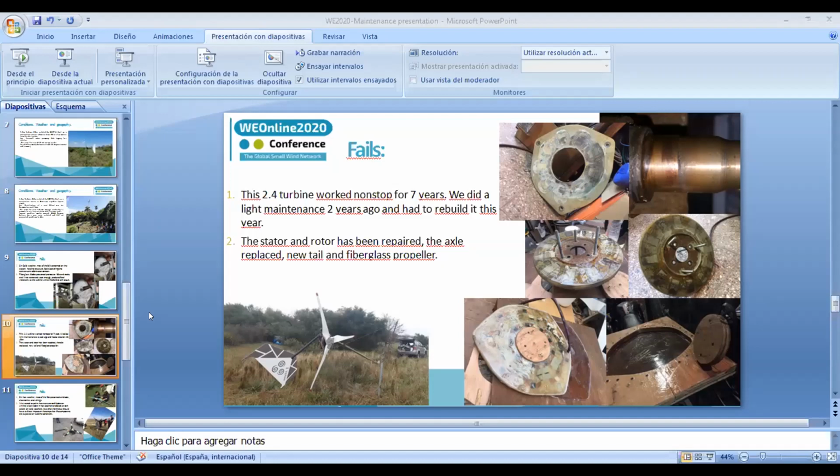But I guess there is also a difference if you use polyester resin, which is of course not watertight in most cases, so water can soak into it. Vinyl ester resin is watertight, and it's the common choice. Then you can use epoxy resin, which is more expensive, but maybe will not always stick as nicely to the steel discs as vinyl ester resin. So I guess it's a compromise, but don't use polyester, I think.